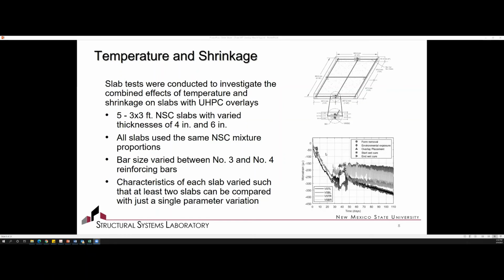This is up to about 100 days. But we were able to capture the behavior of that, look at what stresses were being developed at that interface, and characterize what we'd expect under both the temperature and shrinkage conditions as they were exposed to the environmental conditions.